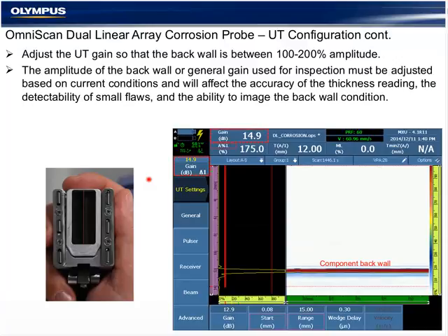The amplitude on the back wall or general gain used for inspection must be adjusted based on current inspection conditions and will differ even between the reference standard or calibration block and the actual inspection, and most of that's due to the surface condition. The gain can be adjusted at any time by tapping on the gain area in the header or by selecting the UT menu general and gain here. This applies gain evenly to all of the A scans in the S scan.